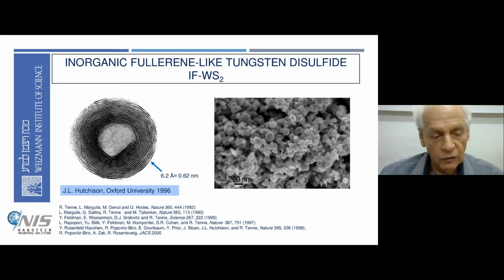I won't go into the details of why it's so different from C60. C60 is made of precisely 60 atoms of carbon, and here you have hundreds of thousands, if not millions, of tungsten and sulfur atoms. So it's much larger - the whole size of these nanoparticles is about 250 angstrom, 25 nanometers, or even larger, counting many, many atoms of tungsten and sulfur.